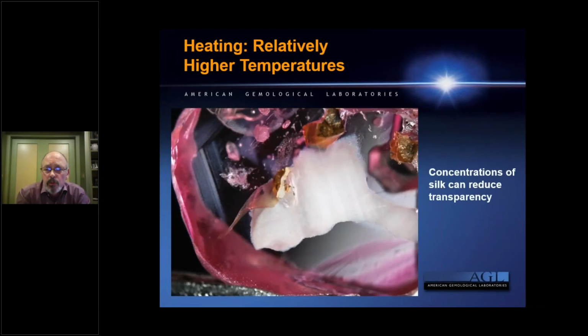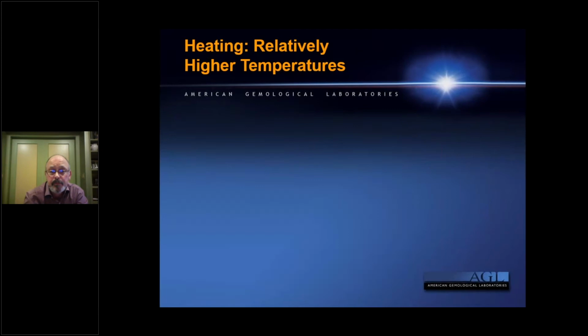This is a piece of rough from Mogok, and here you see in the center part of the image a dense concentration or nest of rutile silk. And this is so densely concentrated that it's actually impacting the transparency of the stone. And so by heating this kind of stone at significantly higher temperatures, or relatively higher temperatures, you're able to completely dissolve this rutile silk and thereby improve the transparency.